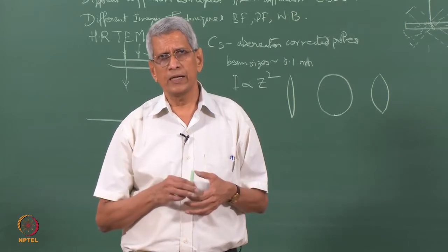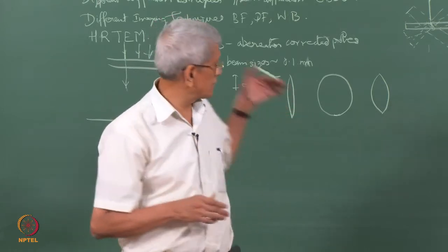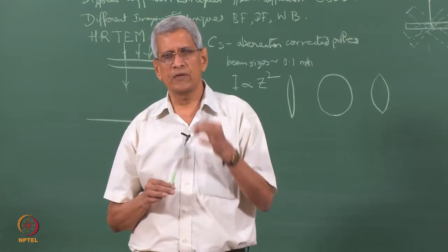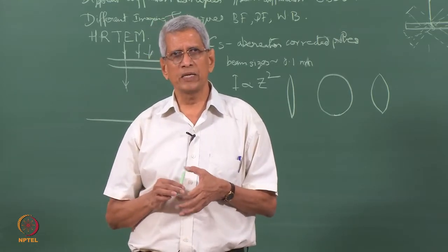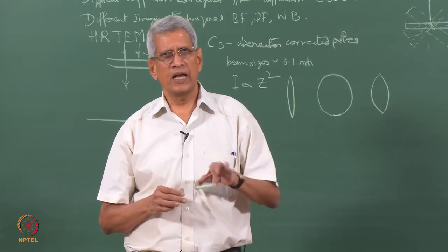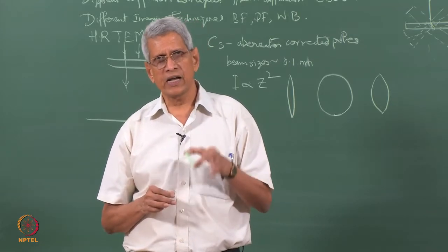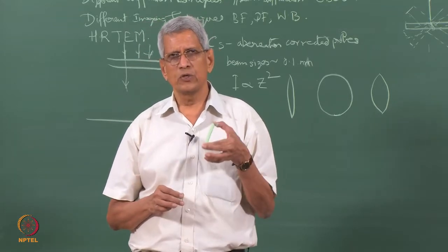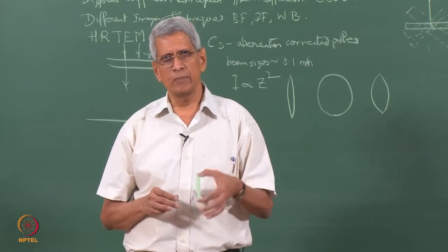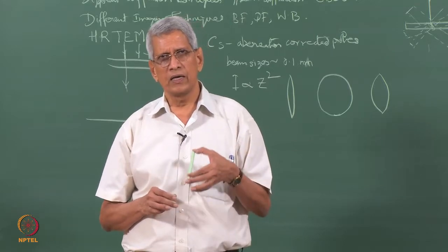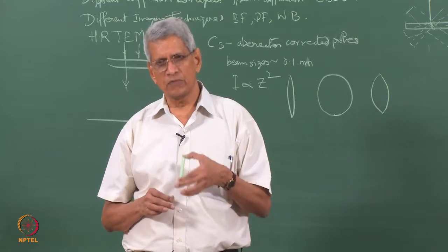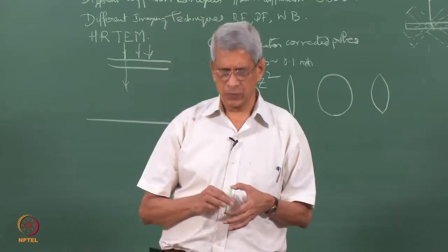Doing it on an optical scale with light scattering is easy, whereas in an electron microscope, especially as we are dealing with diffraction contrast, depending upon the different orientations, if we tilt slightly the contrast varies considerably. So, one has to take a lot of care to see to it that the same diffraction spot is used, irrespective of the tilt which you have used to collect that image.